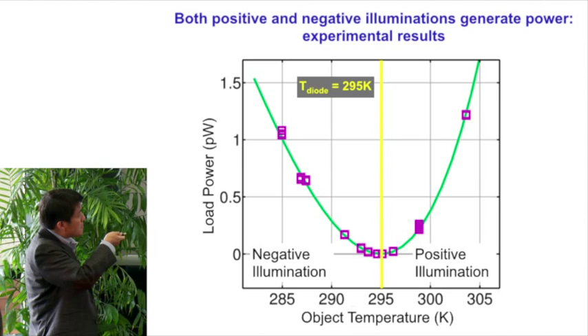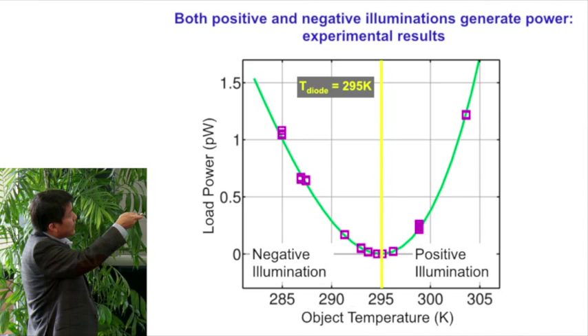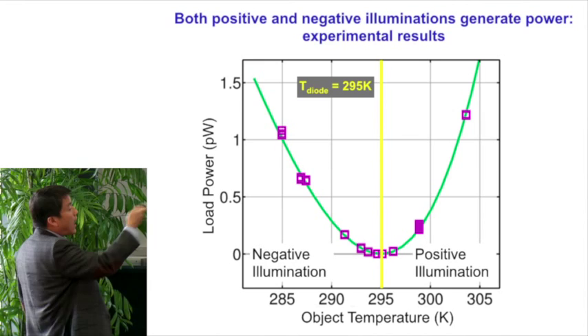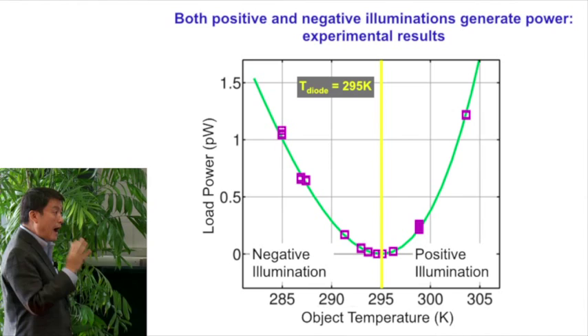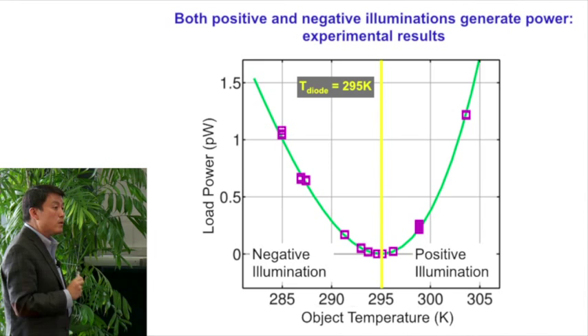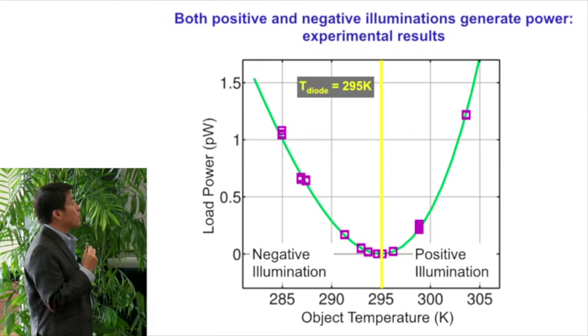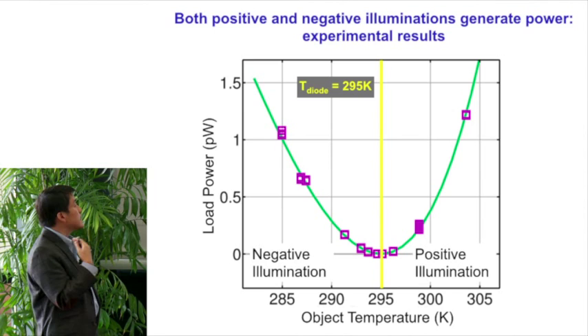And this is the measured power as a function of the surface temperature. The diode itself is at 295 Kelvin. And when it's facing a hot surface and when it's facing a cold surface, on both sides you can actually extract electrical power out of it. Now, the diode that we use is a long wavelength one and is completely unoptimized for this kind of purpose. It's just something that we basically bought commercially for typical photodetection.